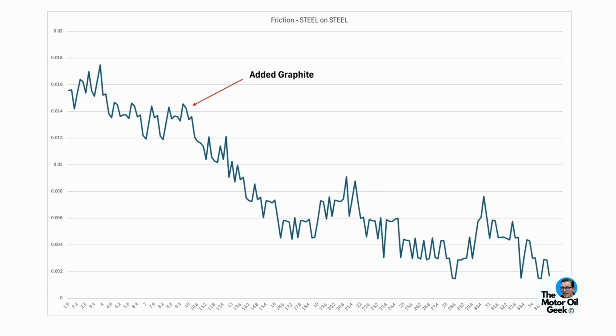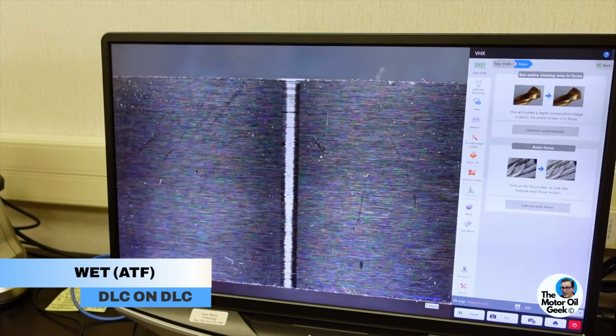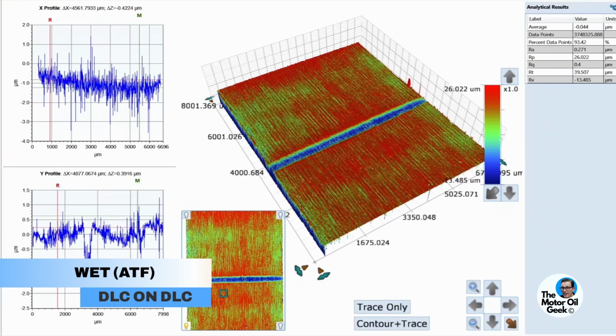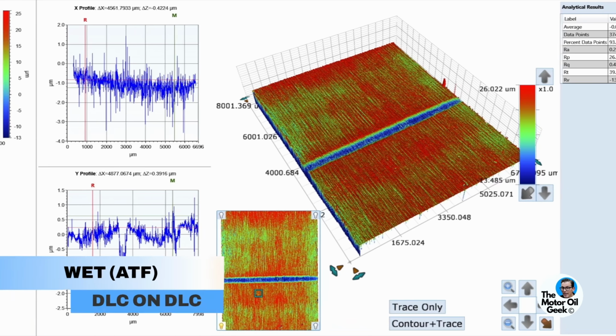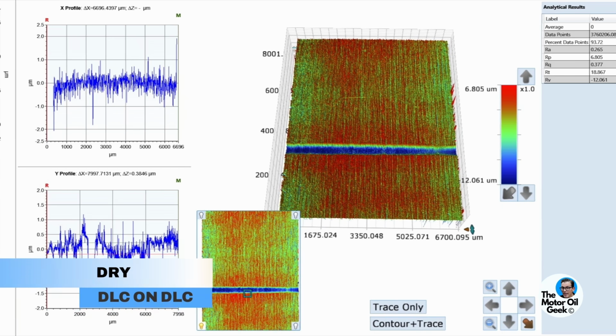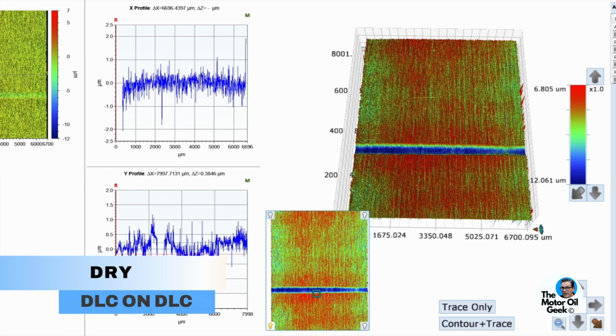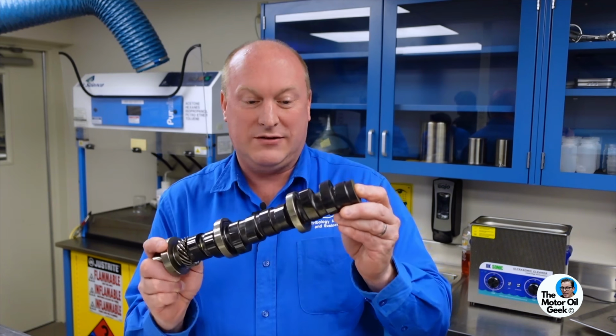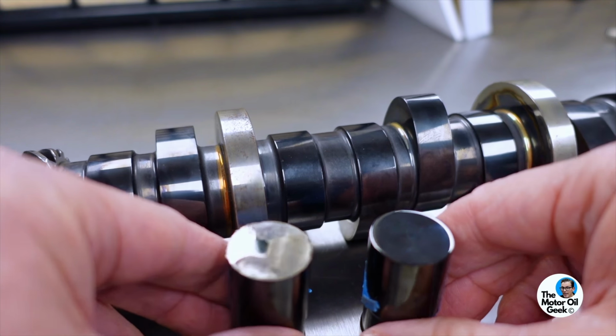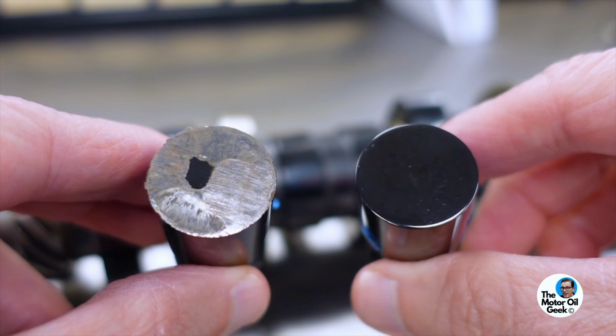So dry lubricants are excellent, but if you try and get too clever with them and you put them in, say, an engine and you do a DLC, you have to think about what your additive package is in the oil to make sure that they're all going to work nicely together, because your oil is a lubricant and your dry DLC is a lubricant. So they still need to work together. An example of that is here we have a camshaft that's been DLC coated on the tappets, and we saw this one just now. Well, what happens if you don't make it work properly is you end up with this looking like this.